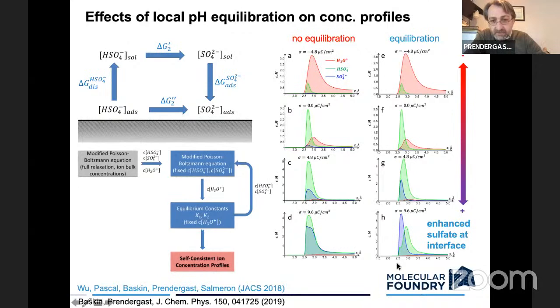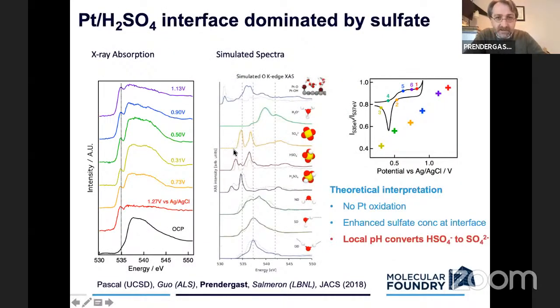It's not everything, but you're definitely displacing or removing bisulfate from the interface, and the free energy is lowered by enhancing the number of highly charged dianions at the interface. So that was an interesting observation, and seemed to make sense when we thought about it more. And this is how we then explained why the experiment was seeing only the sulfate as being the dominant component at the interface. So that's just the detail here. So it's not just a matter of providing the isolated species and their spectral signatures, which you can't do an experiment anyway, but also this inclusion of some physical modeling of what we expect the situation to be as all of these species interact and exchange between their different populations. So local pH in this case.